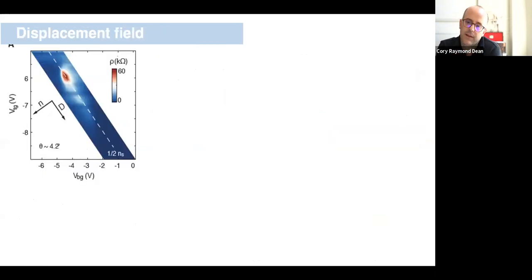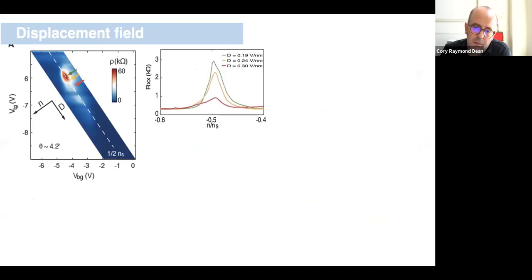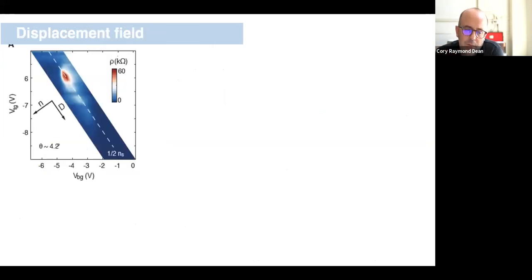Okay, so we can study that a little bit more. One of the things we did early on was to look at displacement field dependence. So in this image on the left here, I don't show it, but we can have a gate on the bottom of this device and a gate on the top of this device. And in combination, those 2 gates allow us to independently tune the band filling and transverse displacement field. So we can sit at fixed filling and vary the transverse displacement field. And what we find when we do that is that this half band insulator actually exists only over a fairly narrow range of displacement field.